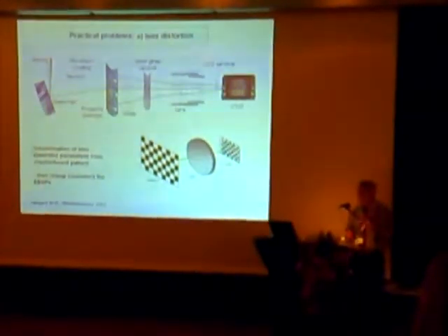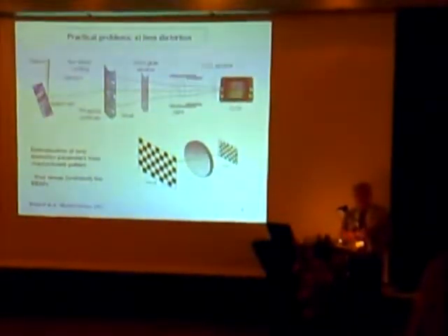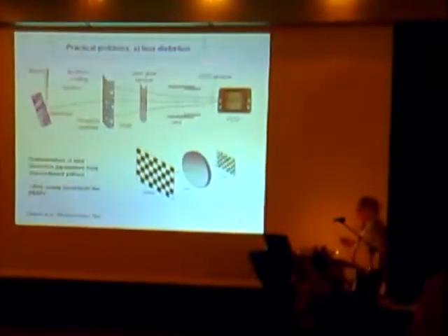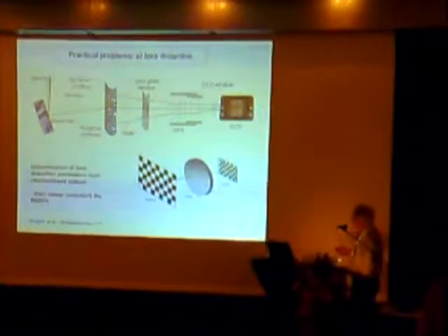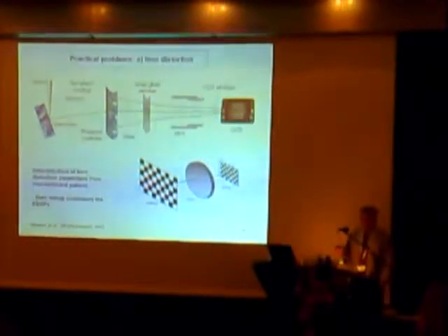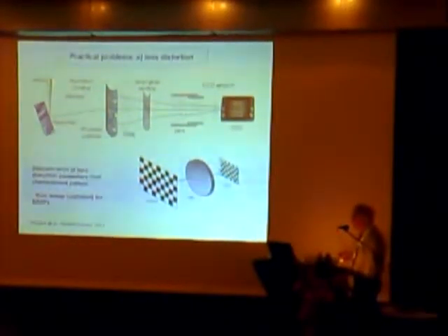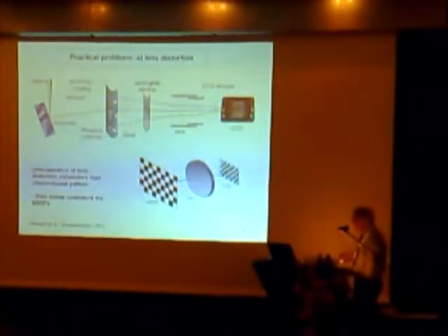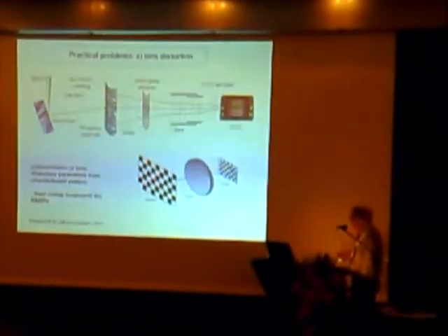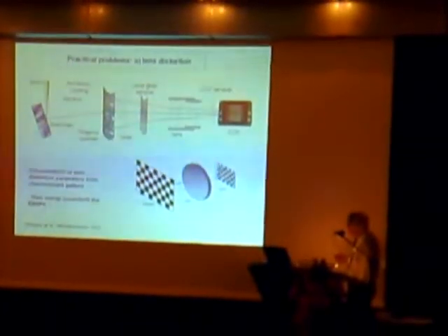The second point is that the one that survives, in fact, has its trajectory slightly deformed by your lens system. This was actually pointed out to us a couple of years ago, and so we worked on how to correct for this. In fact, the correction is relatively simple. Basically, you take some kind of checkerboard pattern, take away the phosphor screen, and look at the checkerboard pattern through your camera system.